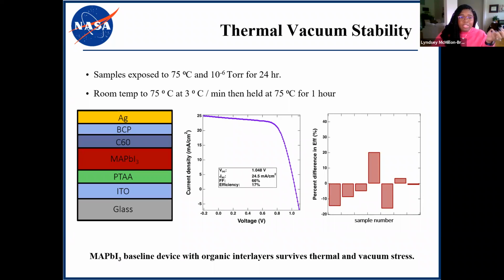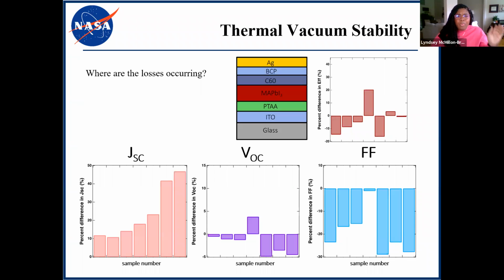So the takeaway here is that our baseline MAPI device with organic interlayers does survive our thermal and vacuum stress. Now, we want to take a closer look at these results and really determine where the losses are occurring. So here we're breaking down short circuit current, open circuit voltage, and fill factor figures of merit for each discrete sample that went through this experiment.